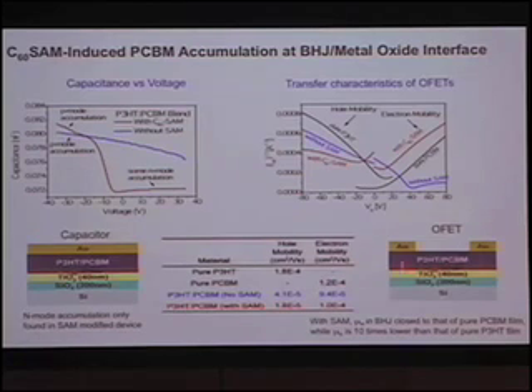If I have a C60 SAM, this is a red layer here, and if I can nucleate nicely the C60 concentrate as an interface, then I will selectively have only the improved electron transporting property, which is actually proven in here. Okay, so you have C60 with SAM having much higher mobility compared to without the SAM. Okay, so this gives you some direct evidence. Okay. This does have some effect on that.